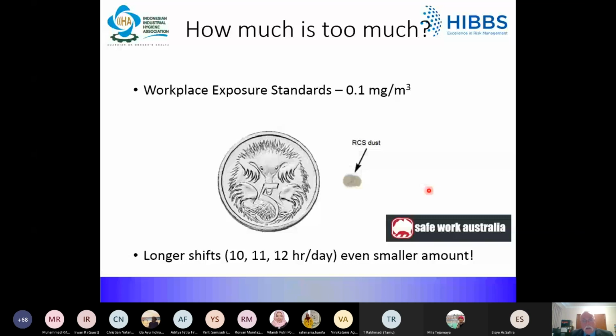Now, recently in Australia, the 8-hour time-weighted workplace exposure standard was decreased to 0.05 milligrams per cubic metre. And this is an extremely low exposure standard for a very common hazard, and one that's particularly prevalent in the construction industry.